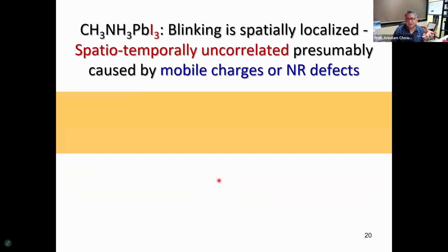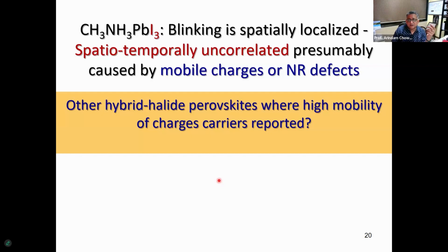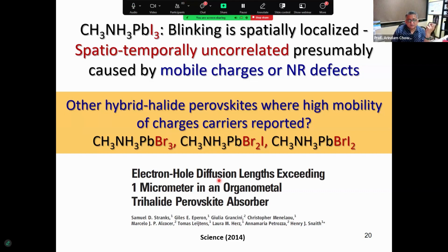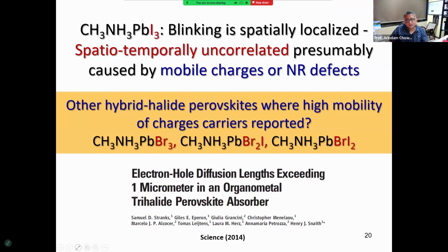Now, at that point of time, we were exploring other halides of methylammonium lead halides. We were not only looking at iodide; we were thinking that there are other halide perovskites where high mobility of charge carriers have been reported, right? This is a paper in Science by Henry Snaith that talked about more than 1 micron diffusion lengths that were reported for bromides and iodides. So we started looking at bigger, micron-sized crystals of these materials, mostly bromides as well as iodides. A lot of people were working with iodides, and we started working with bromides.